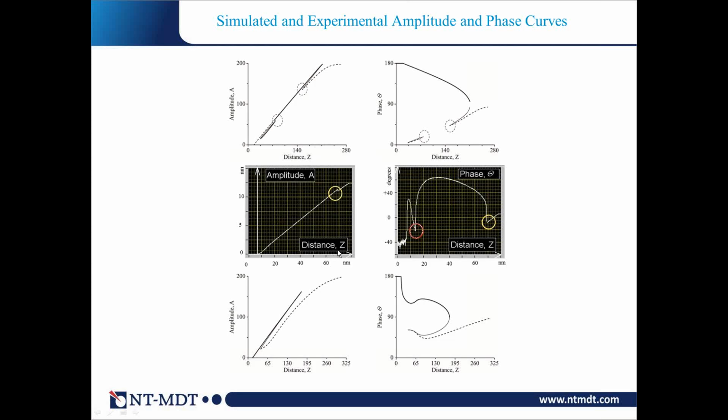There are some jumps of amplitude or the phase, because here you also see a jump from, let's say, attractive interactions, because this was below the zero level, to repulsive interactions. And in this case, if you stay at set point conditions where that happens, in images you can have patches of different contrast, which you can be confused with. But this really shows what is going on, and this phenomenon is known as a bifurcation, the transition from different branches. And you see the unstable branch is not realized, but